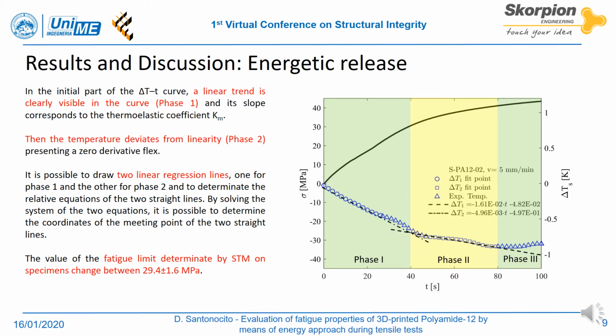It is possible to draw 2 linear regression lines: the former for the first linear phase, the early stage of the temperature signal, ΔT1 fit point series, and the latter for the second phase, the last stage before the sudden increase in the temperature signal, ΔT2 fit point series, not taking into account the temperature values near the slope change in the experimental temperature series. Solving the system of equations, it is possible to determine the intersection point of the 2 straight lines. The corresponding value of the applied stress, sigma limit, could be related to the macroscopic stress that introduces the first plasticization phenomena in the material.